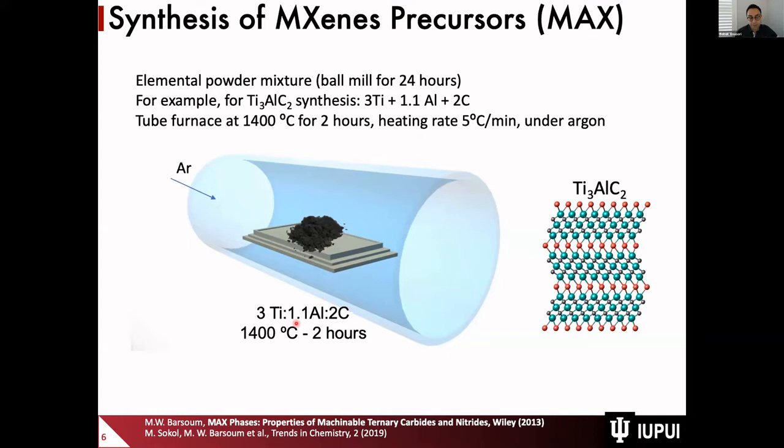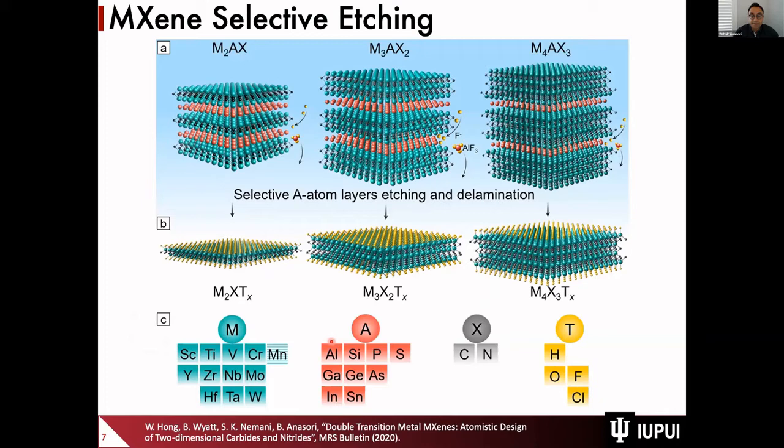For example, the famous Ti3AlC2 can be synthesized by mixing the stoichiometric ratio of titanium, aluminum, and carbon, and heating it to 1400 and holding for 2 hours. And then we can make these two MXenes. All the MXenes I'm going to talk about are synthesized by HF etching. So basically by HF etching, we can remove the A layer elements, mostly aluminum, and turn them to MXene